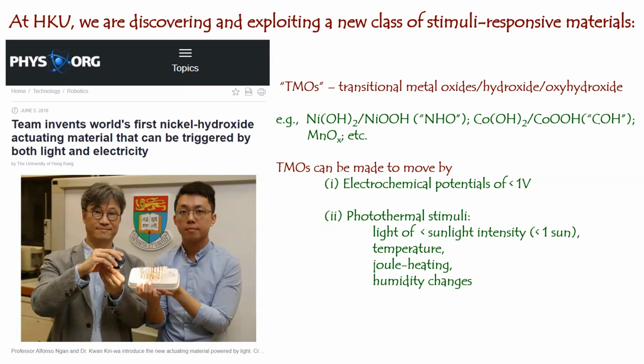So you can shine light onto the material, and it can move. And also the input is very lean as well. We'll be talking about less than 1 sunlight intensity. So even on a cloudy day like today, that intensity will be able to drive the material to move. And temperature rise can be done by Joule heating, which is an easier way of delivering the stimuli because you can use electricity. Or you can reduce the humidity in the environment. The material can also move.